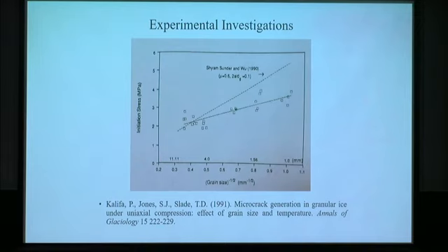I have some more data which plots, in this case, the nucleation stress, the initiation stress in megapascal versus the grain size to the power of -1/2. So basically, if you move down along this axis, you get d to the -1/2. So it's an inverse relationship, 1/d to the half. You can see the data over here. So the nucleation stress increases with d to the -1/2.